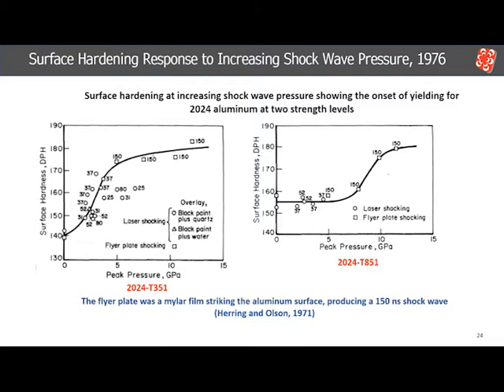These results demonstrated that surface hardness could be used to easily determine the minimum peak pressure to cause measurable yielding in laser shocked metals with just a series of spots of increasing intensity on a metal plate.